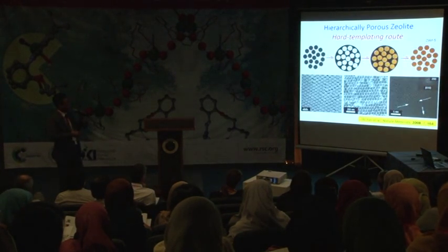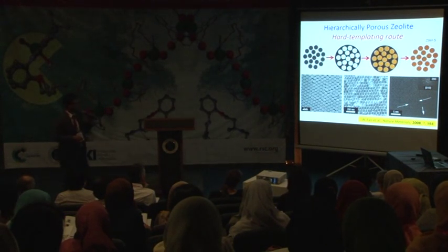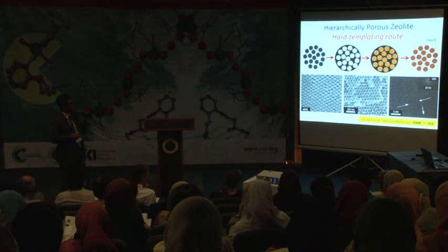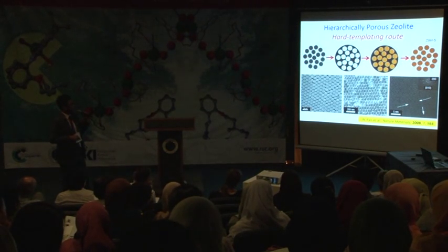So how do we do that? How can we synthesize those zeolites? So this is from literature. They were using hard templating routes to synthesize hierarchically porous zeolite. They started from the monodispersed silica nanoparticles, and they somewhat introduced carbon in order to get a replica of these silica nanoparticles.